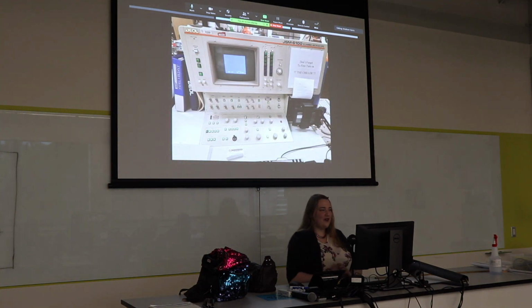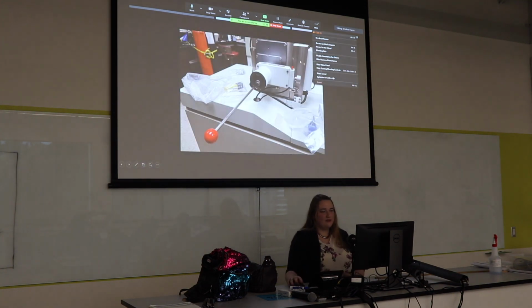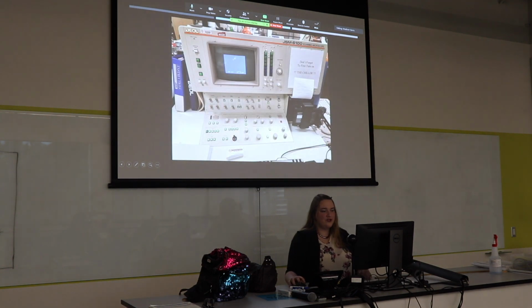And this is the control console. You can see a little screen here. That's where we can observe what our sample looks like, and we can use this joystick and these knobs to move around and see different areas of our sample and also determine how zoomed in we are. The problem with zooming in too closely is the image starts to get fuzzy or snowy, and we have to determine what quality we're willing to risk in order to see really far into our sample.